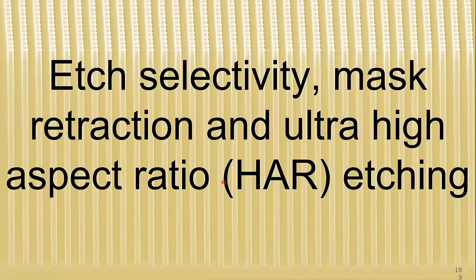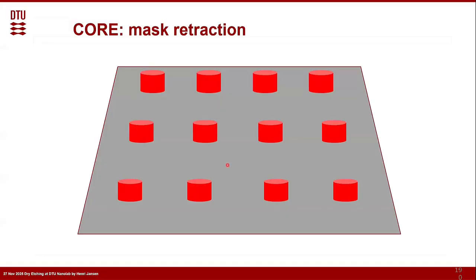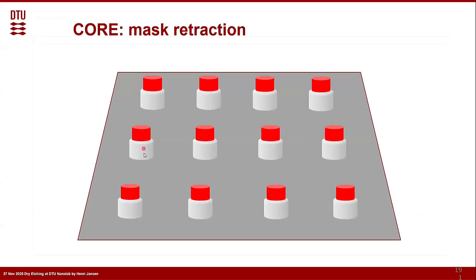And then, okay, now we have to talk a little bit more about etch selectivity and mask retraction, because that's becoming a very important subject. You cannot always use photoresist because the selectivity, especially with the core process, which is using oxygen to etch the silicon, cannot be much higher than roughly 10 or so. How can we improve that? Let's first look a little bit at what happens with resist. Imagine now we have resist on top of a silicon wafer and we start to etch.